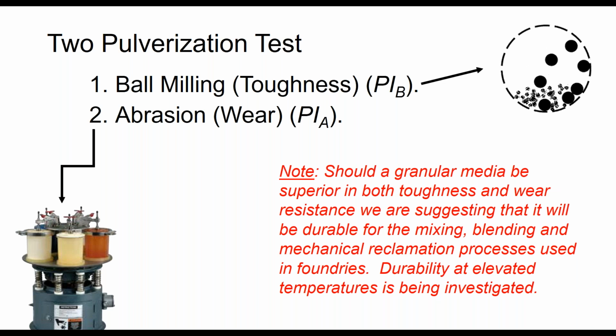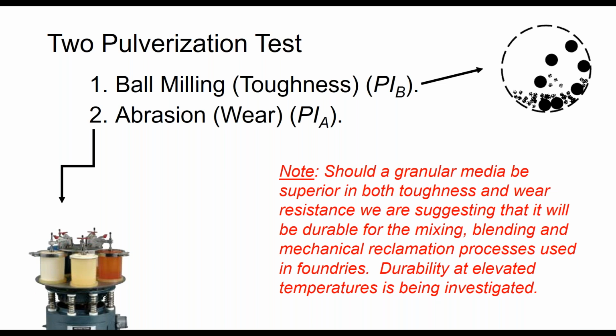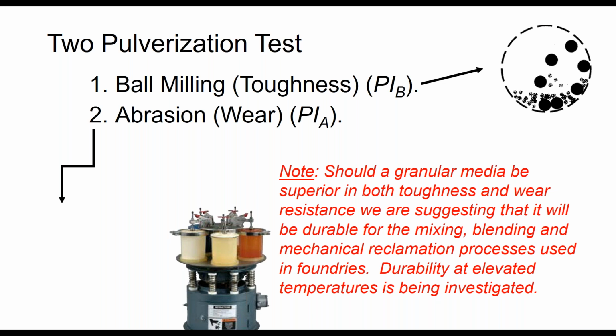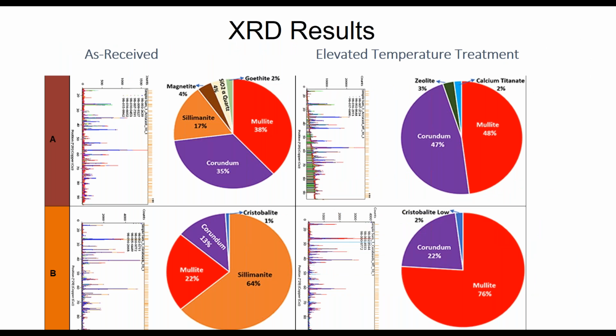But the point is, should a granular media be superior in both toughness and wear resistance, we are suggesting that it will be durable for mixing and blending, and the mechanical reclamation process used in foundry processing for these ceramic alternative media. The durability at elevated temperature is also being investigated in our work. And what we're suggesting here is something that is true for all the media that we would see. On the left, I'm showing just two of the sands that we studied. On the left is the as received compounds that we see in the material.